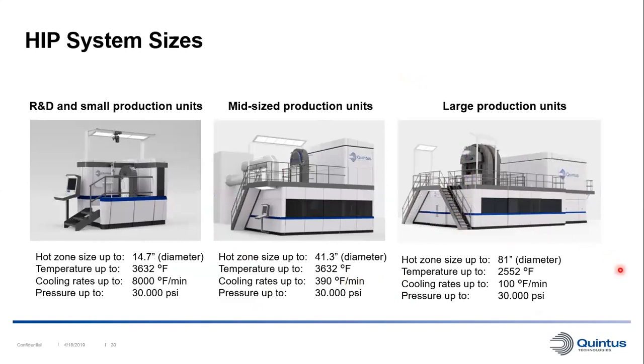Then we have large production systems that are up to 81 inch diameter. This is the biggest one we have ever built, but we can build bigger if needed. These go up to 2,500 Fahrenheit and also have slower cooling rates. And these very large systems can take up to 60,000 pounds of components per cycle.